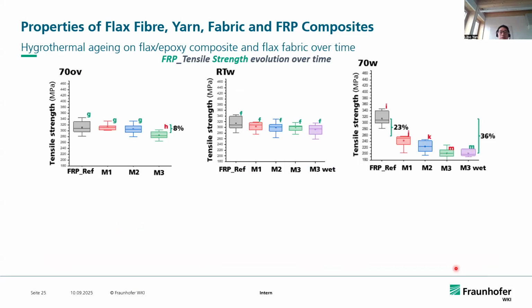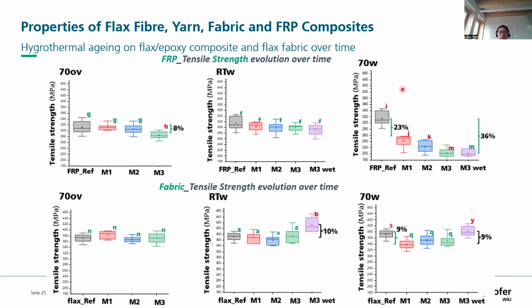How about the hygrothermal aging effect on the flax fabrics? For the first row, we already discussed that we take a look at how, under the same exposure environment conditions, the tensile strength of the flax fabrics will change. As you can see, for the flax fabrics exposed to the 70-degree dry condition, there is almost no change in the tensile strength.